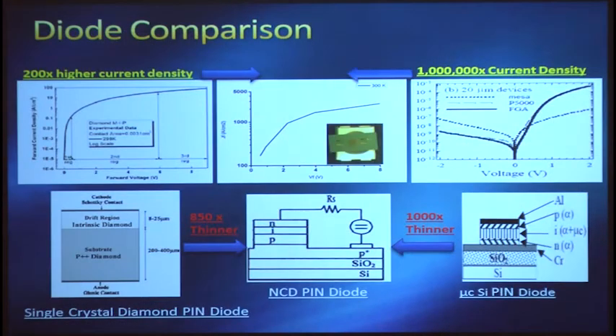How does that compare to what's previously been done, both the state-of-the-art in diamond and the state-of-the-art in silicon? Well, when we fabricated these pin diodes to comparatively demonstrate, we saw some very fascinating things. From an electrical perspective, compared to the state-of-the-art in single crystal diamond, we can put about 200 times the amount of current through that same material. And when we compare that to the silicon-based devices, we can put about 1,000,000 times higher current through the same amount of material.